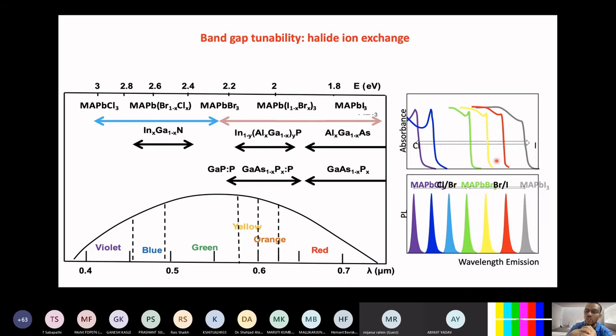If the dielectric constant is low, then the binding energy is high. And the dielectric constant of MAPbCl3 is much lower than MAPbBr3, and it's much lower for MAPbI3, and hence they stay bound together. In silicon, the dielectric constant is close to 12, and the exciton binding energy of silicon is close to 15 meV, and hence when you shine light at room temperature, which is 25 meV, you don't generate any exciton. You directly generate free carriers, and you get the photocurrent out.